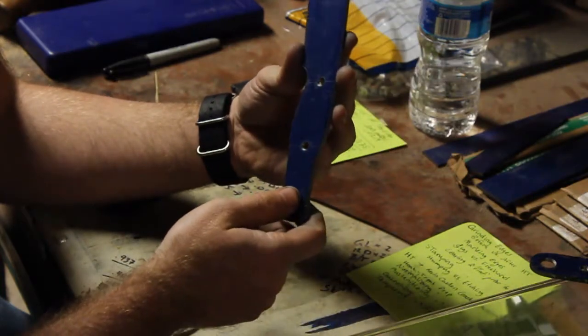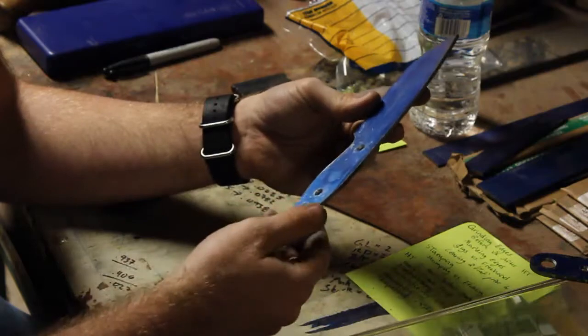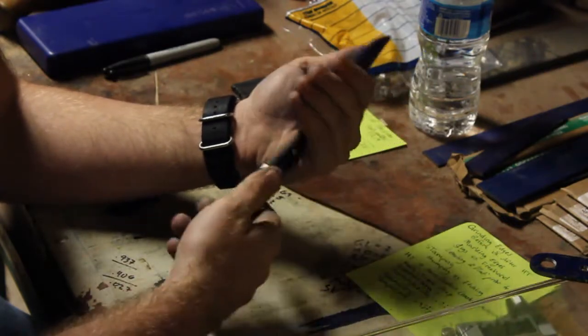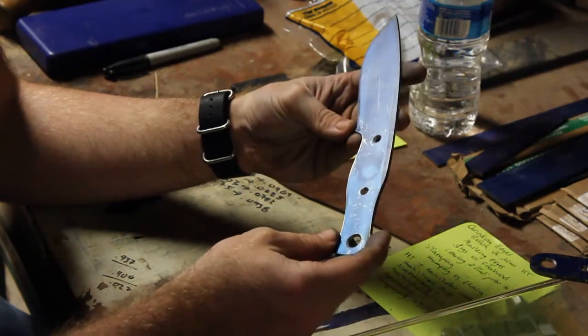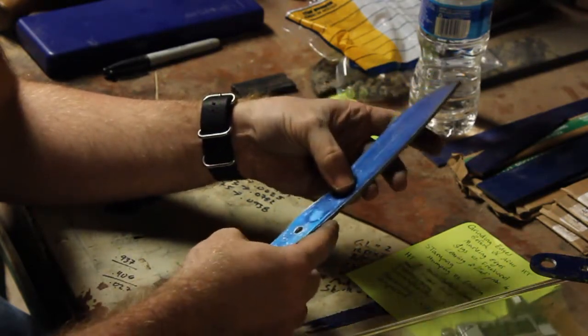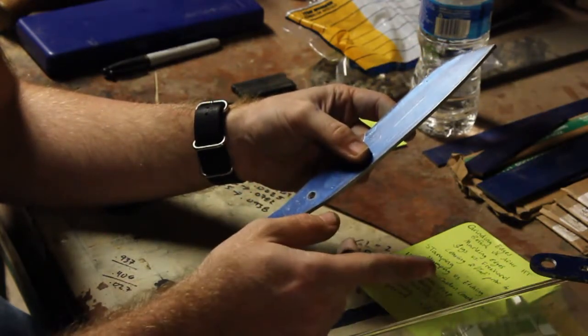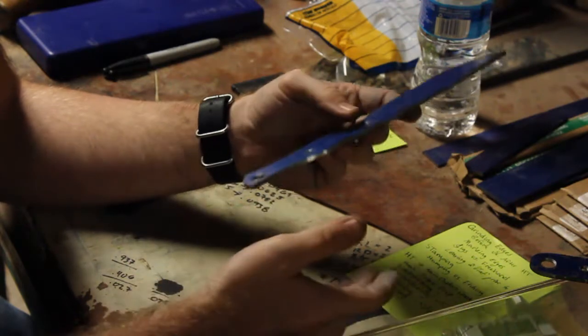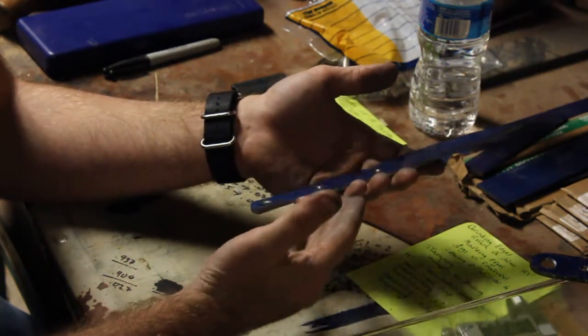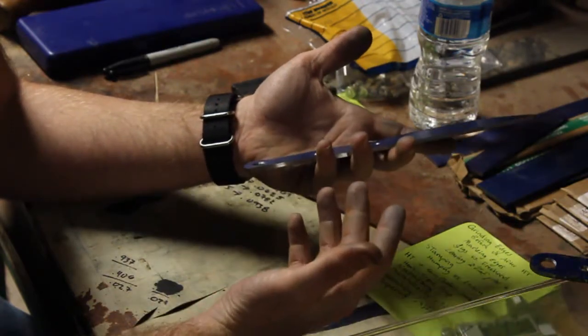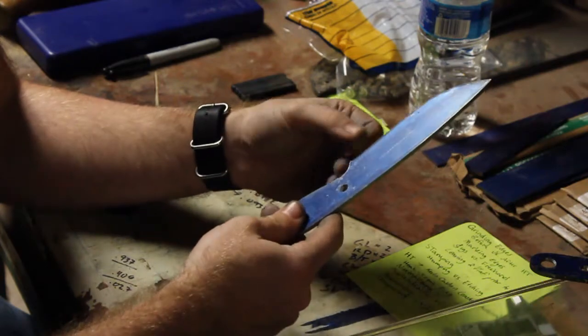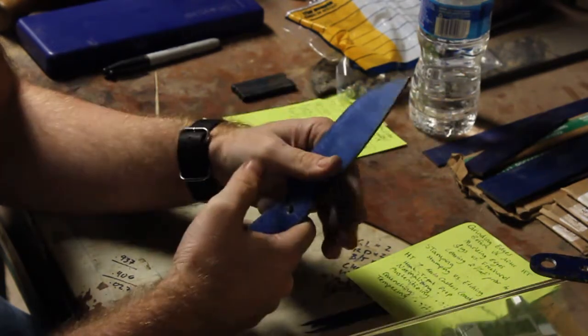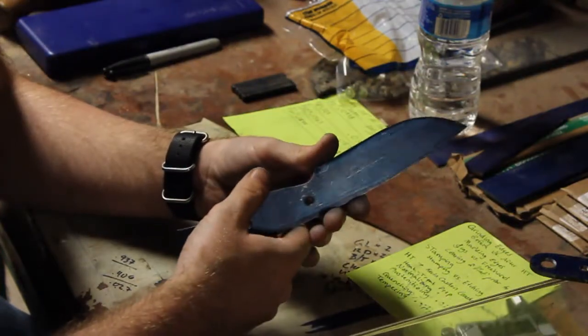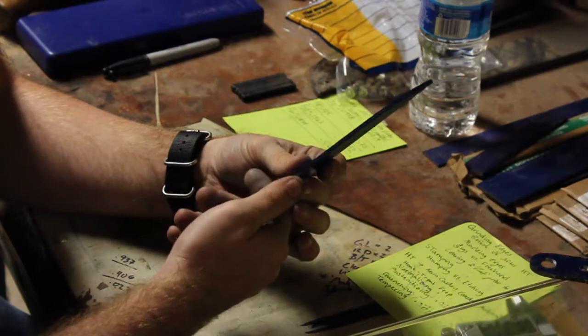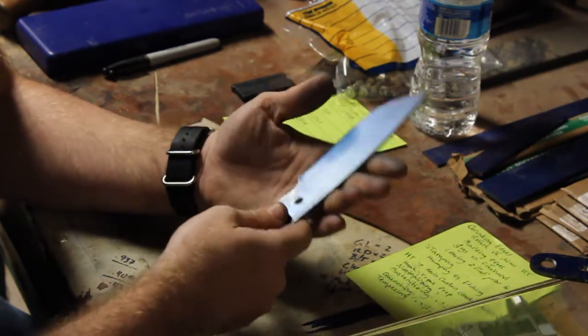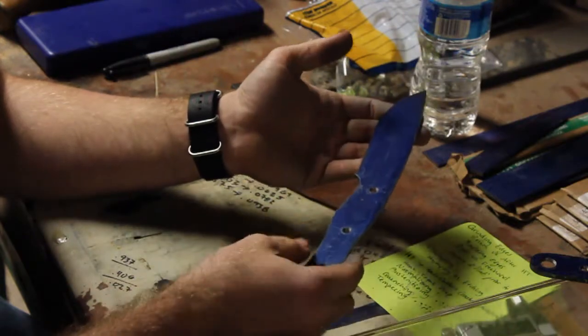The next step is tempering. I triple temper my blades. Again, you can find that information on Kevin Cashin's website. Each cycle that I use is 2 hours long, and from what I've read, more cycles are better than longer cycles. So, is it better to have 3 1-hour cycles or 3 2-hour cycles? I'm not an expert, but I don't think it's going to hurt. 2-hour cycles, triple tempered. I'm quickly approaching diminishing returns, but I know that I'm getting the most out of my steel.